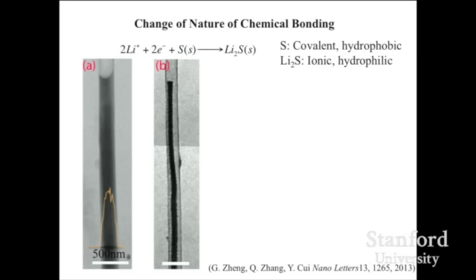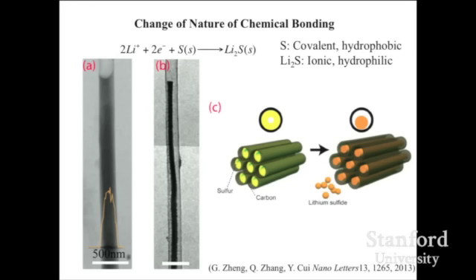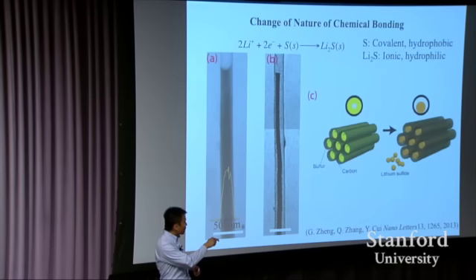This is sulfur embedded into a hollow carbon, in transmission electron microscopy. Once you put lithium in, you start to see the sulfur kind of bead up, become a rod. They detach away from the sidewall. What it turned out to be: sulfur likes to wet carbon, but lithium sulfide is ionic bonding. Sulfur is covalent bonding. That's freshman chemistry right there. The bonding is different. They like different stuff. Carbon likes sulfur, but carbon doesn't like lithium sulfide. And then the polysulfide is so hard to track. The lithium sulfide might be detached away from the sidewall. Electron transport becomes hard. Remember, we need electron transport, we need ion transport. If one thing is screwed up, then you are done, so your capacity will decay.